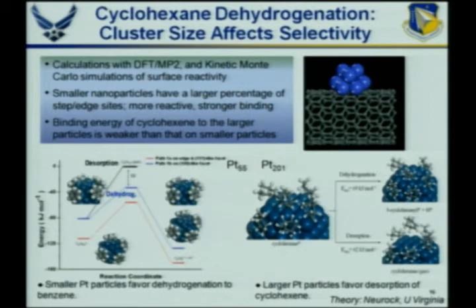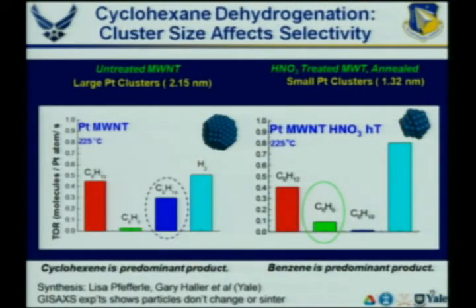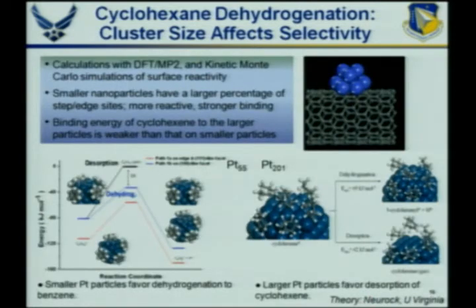And basically, what he found is summed up that in the smaller nanoparticles, there are more edges. If you look back at these structures, in the smaller nanoparticles, almost every atom is on a corner or an edge. In the larger nanoparticles, you have some larger areas that are planes. And those atoms in the middle of the planes are less reactive, and things bind to them less strongly. So what he found with the small nanoparticles is that the lowest energy pathway is dehydrogenation. So the cyclohexane comes in, sticks to the small platinum nanoparticle, and the lowest energy pathway is dehydrogenation. So it keeps losing hydrogens before falling off.